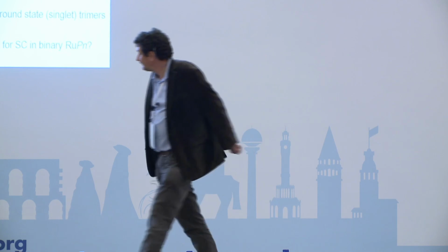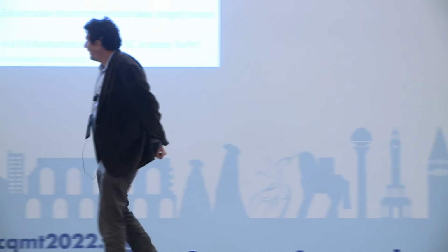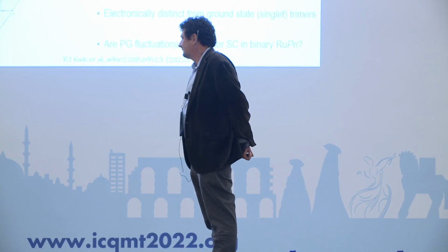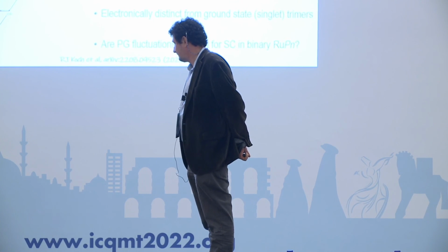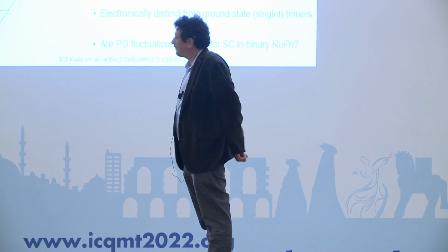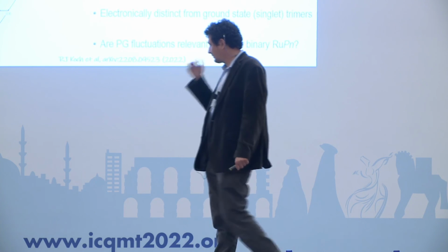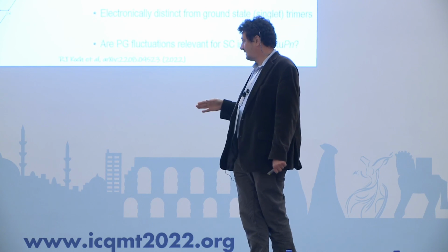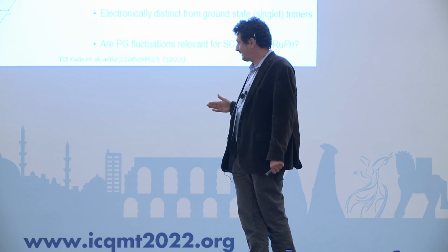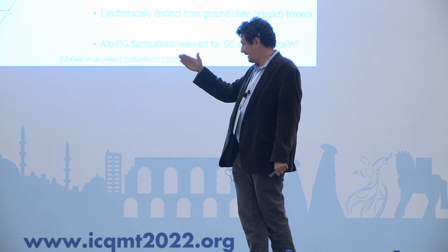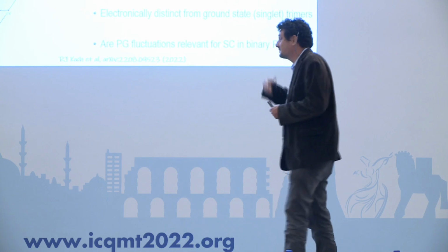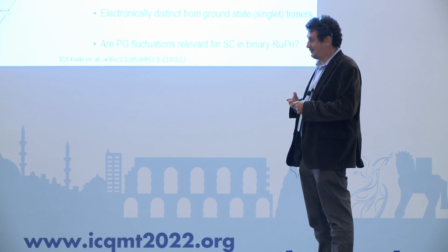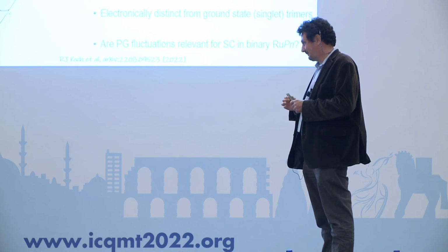I would like to ask what is the symmetry of your superconducting state? For example, the symmetry of your gap? It's a single band S-wave. The only unusual feature of the superconducting regime is that the upper critical field is linearly increasing with temperature and does not saturate at low temperature. So it is declared to be a conventional BCS superconductor.